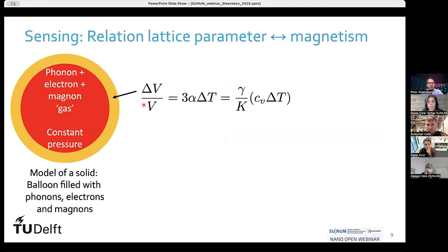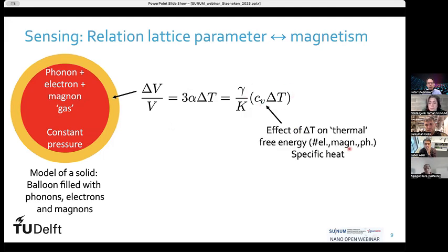Okay, so we can measure this thermal expansion coefficient alpha, but how is that related to the magnetism in the material? To understand that, one can look at this material as a kind of balloon, which is filled with phonons, electrons, and magnons. These are excitations in the material, and they create a kind of pressure on the balloon. If you start changing temperature, for example, if you increase the temperature, you create more phonons, electrons, and magnons, and we're especially interested in these magnons because they are the magnetic excitations in the material. Those properties are related to the specific heat by this equation, which tells us that the number of magnons that you create by increasing the temperature is given by this factor, which is the specific heat.